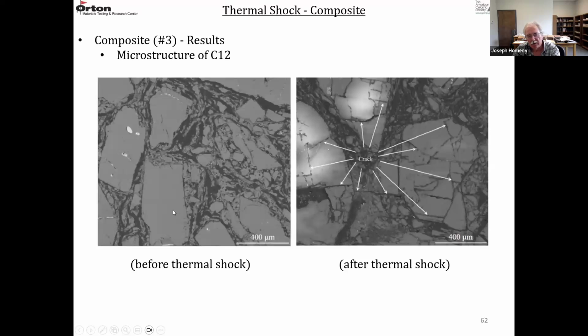So these are polished sections looking at the microstructure of C12 before and after thermal shocking. It's difficult to see the matrix interface, the matrix coarse particle interface cracking, but it's there. But you can see all the cracks in the coarse aggregates after thermal shocking.